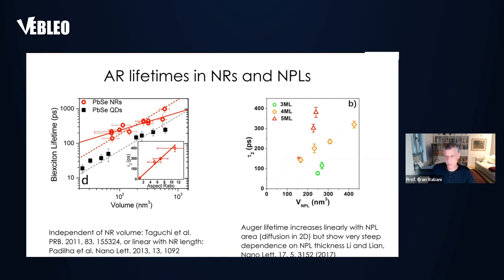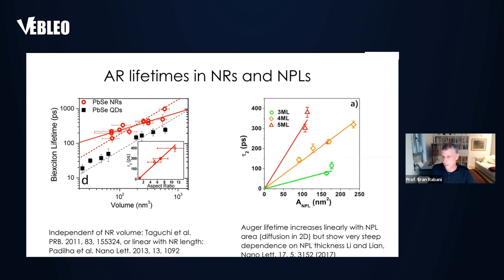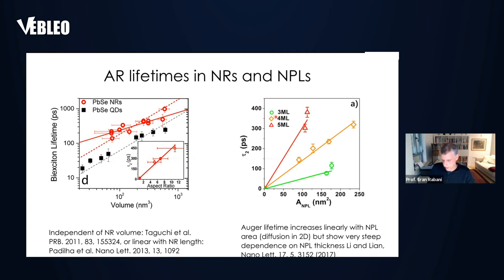One unique feature that these authors used to explain the area dependence is what they call diffusion in two dimensions. They assume that in this nano platelet — which can be as small as 10 by 10 nanometers and only three or four monolayers thick, atomically controlled — two excitons are generated that diffuse just like in the bulk case, and when they meet they undergo exciton-exciton annihilation. This diffusion leads to an areal law for the Auger lifetime as a function of platelet area.